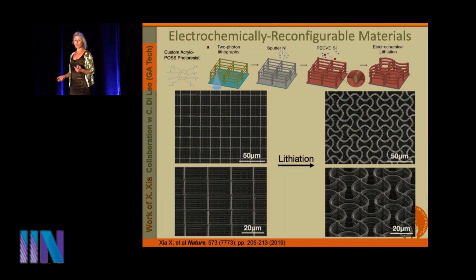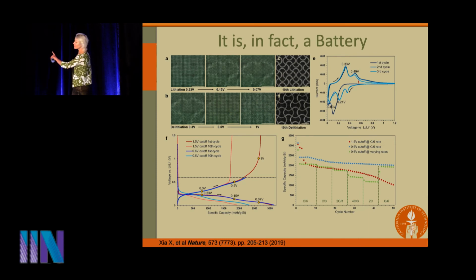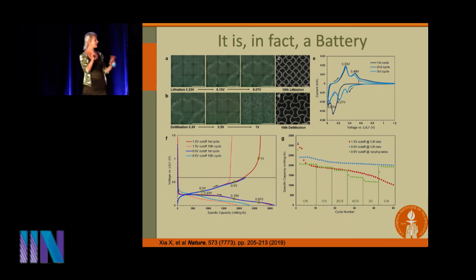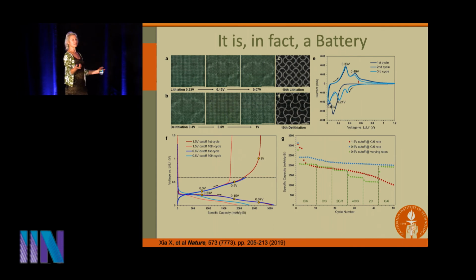And so this is a good situation because instead of cracking, which is what we would expect for silicon, what we're observing is that these beams are bending out of plane. And so this is a true battery, just to show you, this is not just pretty pictures and videos, it is in fact a battery. So for the 0.6 volt cutoff voltage, we can see that here's the specific capacity. It's doing a pretty decent job. It's not the world's best battery. It's an okay battery, but it is a battery nevertheless.